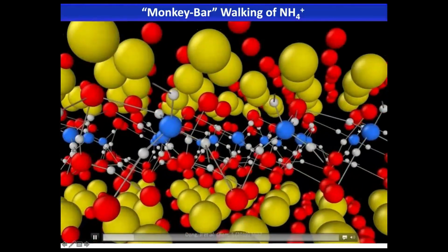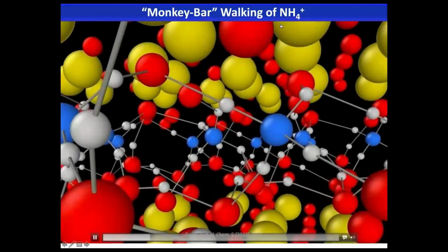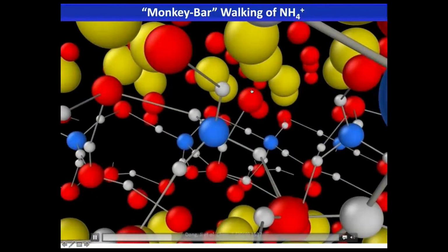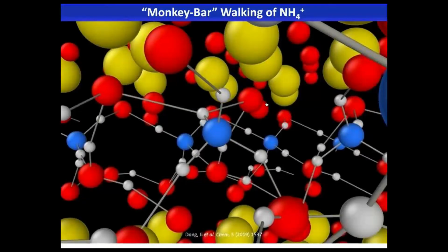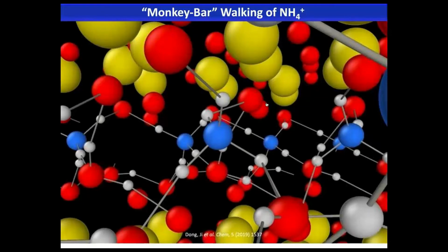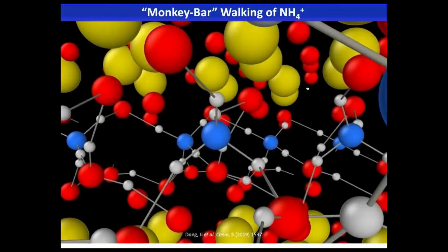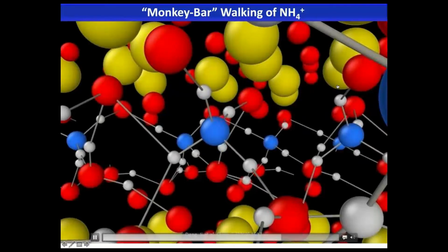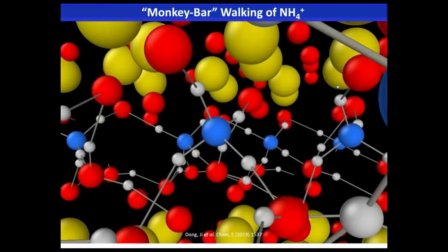And you can see that different from spherical ions migrating, you have ammonium, which is a tetrahedron. It's going to walk inside the lattice like a monkey bar walking, right? Well, because of the directional interactions, because of the hydrogen bonding between the hydrogen atoms of ammonium and oxygen of V2O5. So you're going to have the transference of this ion. It's not going to be sliding. It's going to rotate, right? It's going to rotate. And we need more computation to see whether rotating is really faster than sliding.